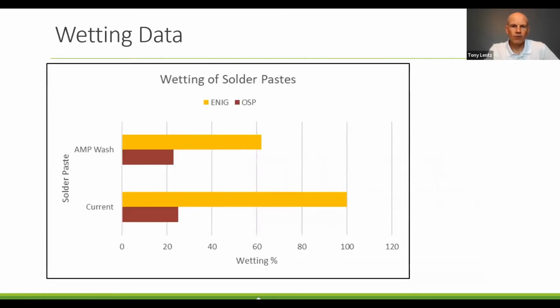Here's wetting data for amp wash versus the current solder paste. The golden colored bars for ENIG surface finish and the dark red bars for OSP. You can see the wetting on OSP is almost identical on these two. Very low wetting or spread percentage there in the low 20s, which is pretty typical for OSP.